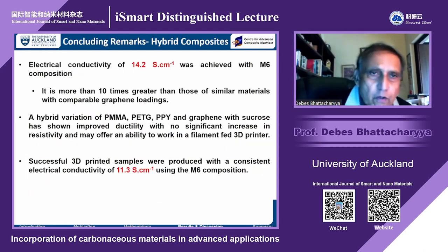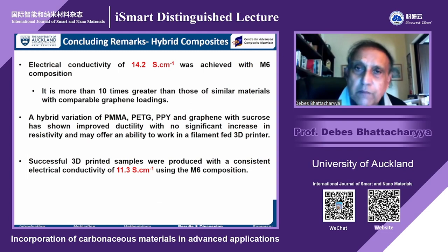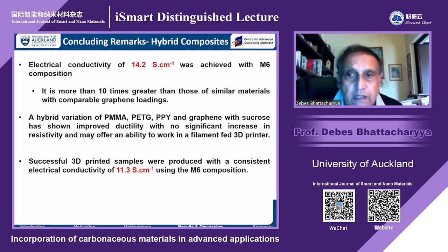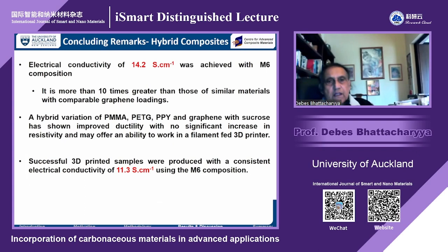So now, concluding: an electrical conductivity of 14.2 Siemens per centimeter was achieved with the M6 combination, and a hybrid variation of PMMA, PETG, PPY and graphene with sucrose has been shown to improve ductility with no significant increase in resistivity. So electrical conductivity did not decrease very much, but because of improved ductility, we could feed the filament through the 3D printer, no problem. And with successful 3D printed samples, we lost a bit of conductivity.